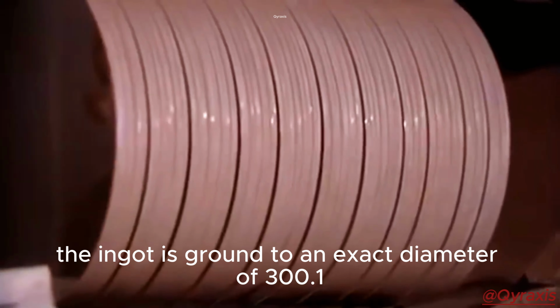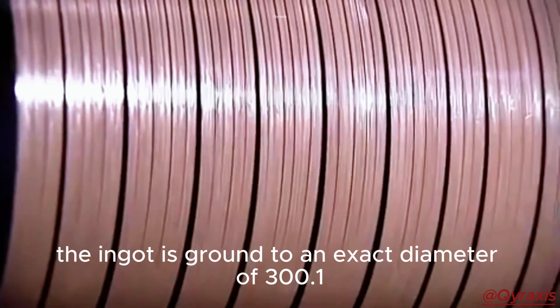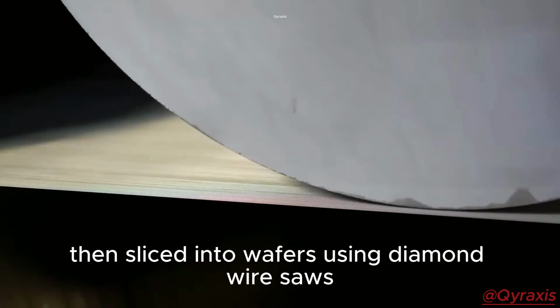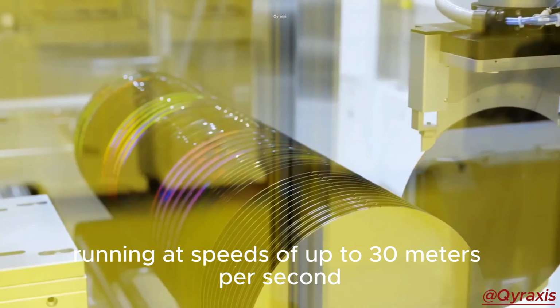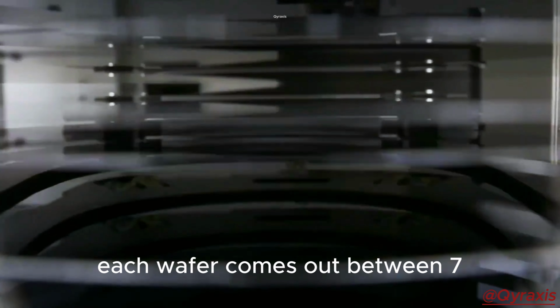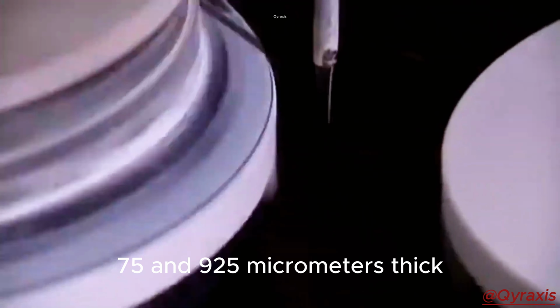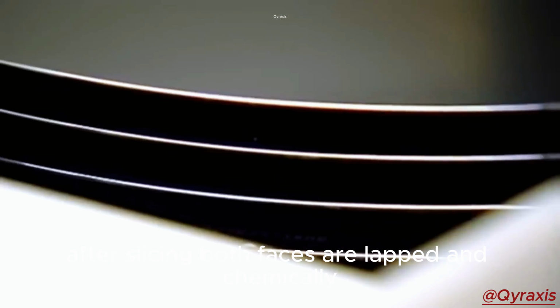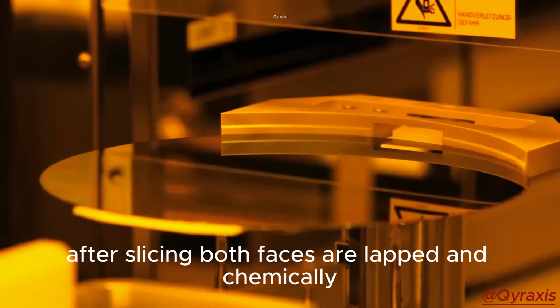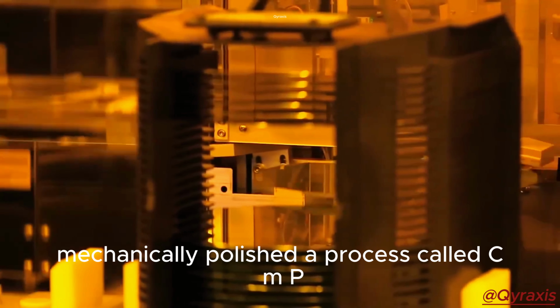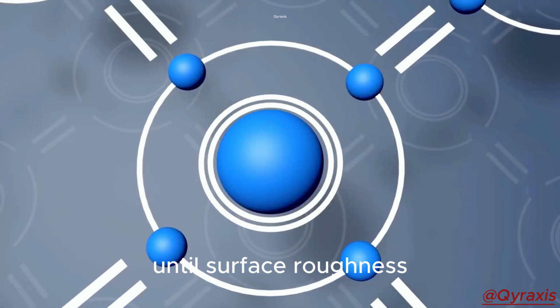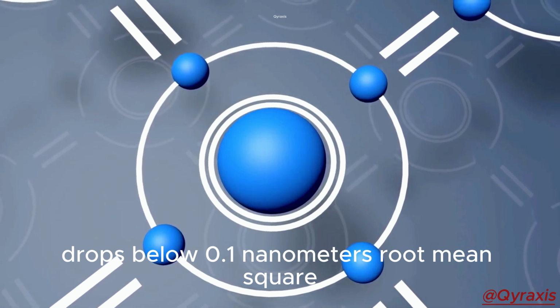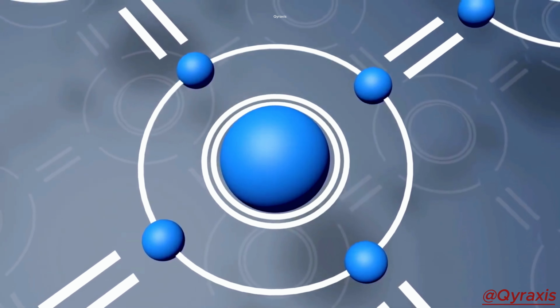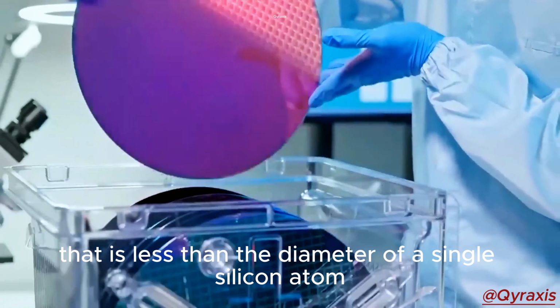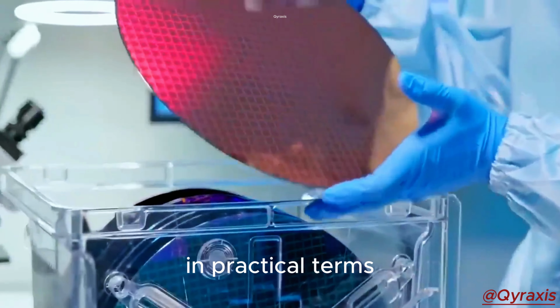The ingot is ground to an exact diameter of 300 millimeters, then sliced into wafers using diamond wire saws, running at speeds of up to 30 meters per second. Each wafer comes out between 775 and 925 micrometers thick. After slicing, both faces are lapped and chemically mechanically polished, a process called CMP, until surface roughness drops below 0.1 nanometers root mean square. That is less than the diameter of a single silicon atom in practical terms.